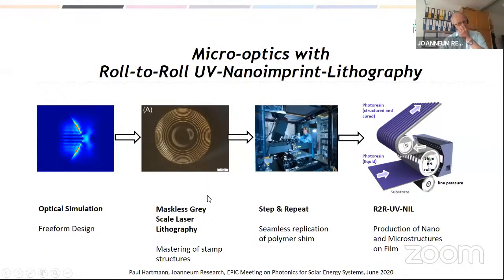So with this maskless grayscale process, we can do a very good and very accurate mastering, which we transfer onto larger areas with a so-called step and repeat process. This step and repeat process is a semiconductor process for replicating semiconductor structures onto UV resins, usually in an 8-inch wafer size. But we have built a machine which does that to produce shims for roll-to-roll imprinting.